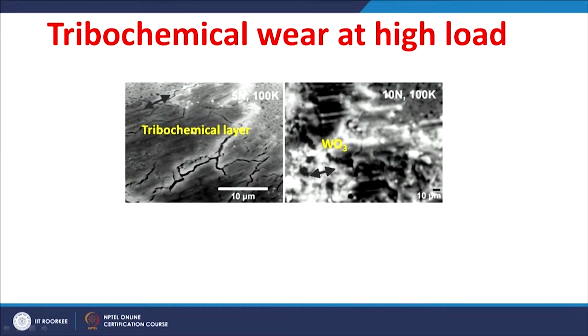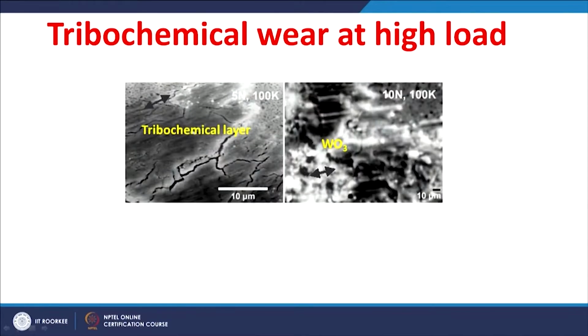That indicates there is a chemistry difference in the layer, and you can see with increasing load again this chemistry difference, the contrast difference, increases. Again, you can see there is a black region, a white region and a bit grey region. The black region is the normal WC surface, and the white region is mainly rich with the heavier elements